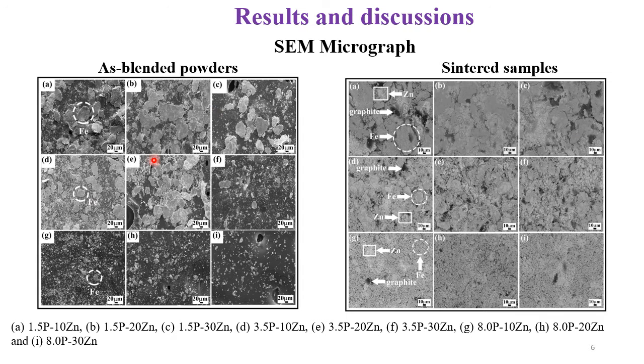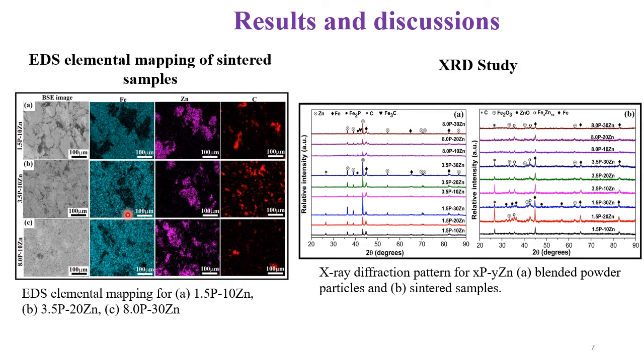So the SEM micrographs show that as we have increased the phosphorus content of the pig iron sample, the particle size decreased. As you can see here, in the 8% phosphorus hybrid sample, the particle size is much lower as compared to the 1.5 and 3.5. And the sintered sample shows segregation of zinc in the pig iron matrix, and the segregation becomes more uniform as we further increase the phosphorus content of the HPPI samples or the hybrid samples. So the EDS elemental mapping of the sintered sample shows the distribution of zinc in the iron matrix, and it is more uniform in the case of the 8% phosphorus hybrid samples.